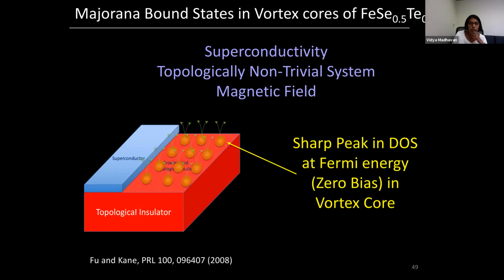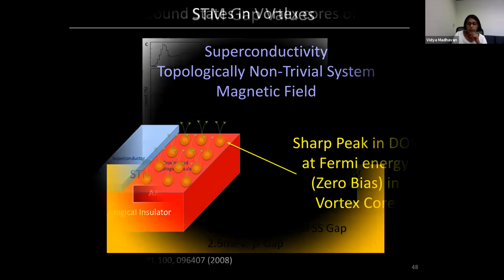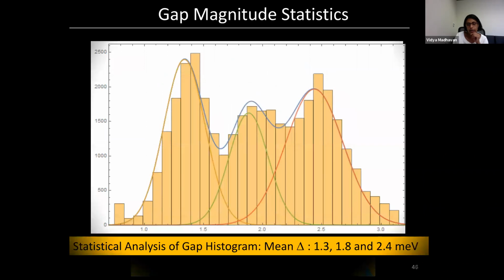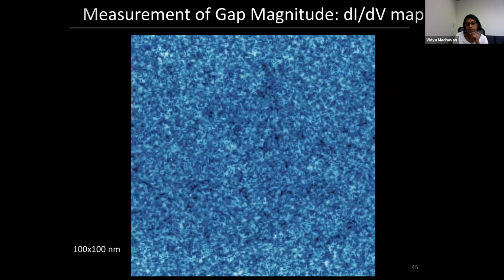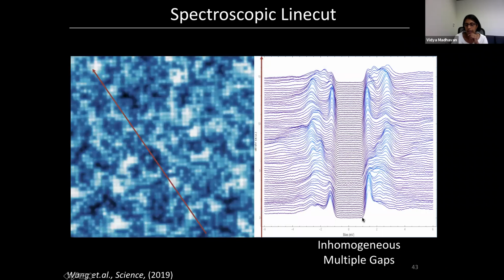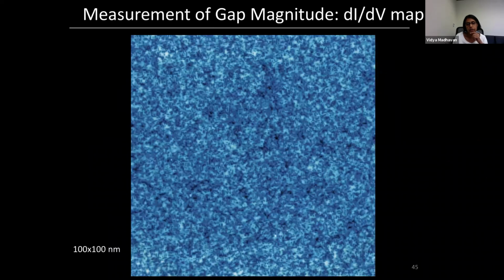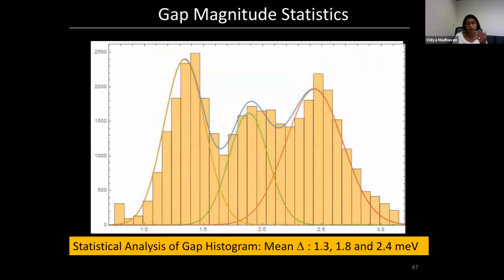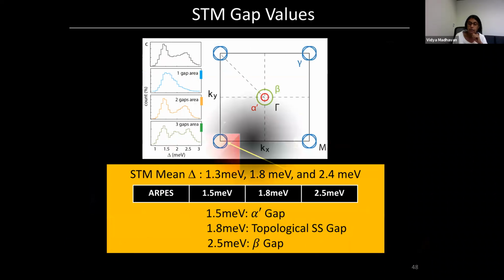All we need to do is turn on a magnetic field. And the question is, what should we see? So remember that in a superconductor, let me just go back here. In a superconductor, there is 0 density of states at the Fermi energy. So if I measure the density of states in this field of view and plot it as a function of position, right? It should be 0 everywhere. So this whole field of view should be dark, black, because it's 0. So that's what you would see if I measured the density of states without a magnetic field. So that's what it should look like.